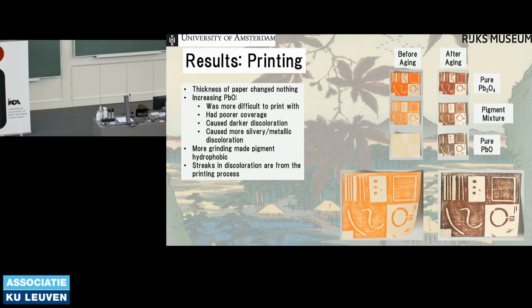During aging, I found the reason for the streaks that were apparent: it was a byproduct of the printing process. On prints that were initially printed very even with very few clumps and streaks, discoloration was generally very even. When printing with a brush such as you use here with very stiff bristles, it's very easy to leave behind streaks on the paper that become more apparent when the contrast between the pigment and the paper increases after discoloration, as you can see here. The other pattern observed in the Rijksmuseum prints, the haloing, was not replicated, and as a result, I could not conclude why it was produced.